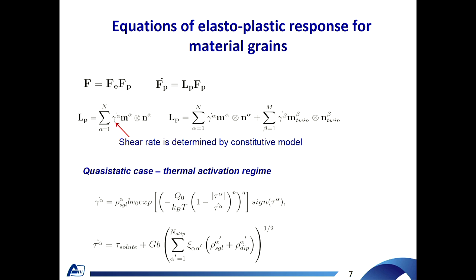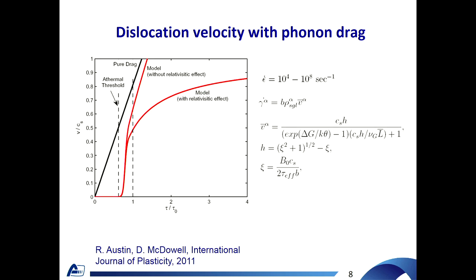Crystal plasticity finite element method is usually used for modeling different metallurgical processes. The deformation rate is very low. It allows to consider thermal activation regime of dislocation motion only. But in our processes deformation rate is from 10 power 4 to maybe 10 power 8 inverse seconds. So we have to consider a phenomenological drag regime also. We use it in the form from this article.